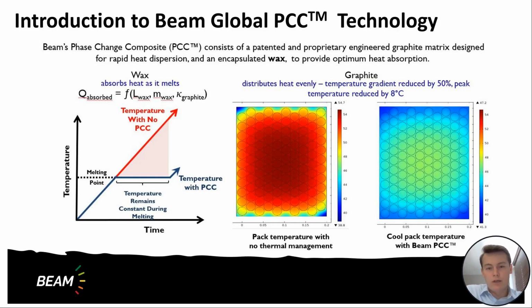So diving into the phase change composite, or PCC technology, it's a composite material made up of compressed expanded graphite and wax, where the graphite is used to rapidly distribute the heat generated from cells during discharge and charge, and that's to enable uniform battery pack temperatures. A battery pack is a weakest-link sport, meaning that if you have hot spots in your battery pack, those temperatures cause rapid battery aging around that specific hotspot in those cells. And obviously this draws down the life of your battery pack.